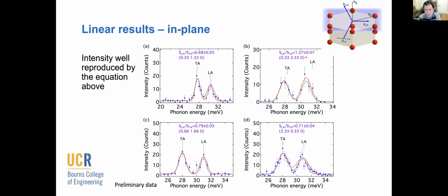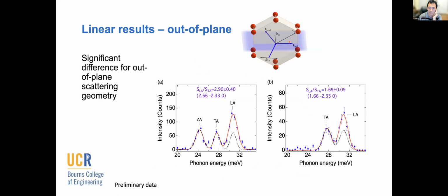non-result. It turns out that when we flip the crystal in a later experiment, and by the way, if you are doing scattering in those two geometries with neutrons, you should see no difference, simply because this doesn't change the phonon polarization vector, and this doesn't change how the neutrons are going to be scattered off the periodicity of the lattice in this material system. But we see a large discrepancy between the longitudinal and transverse intensity ratios in our experimental result and the simulation. You see it's definitely different from what we would expect.